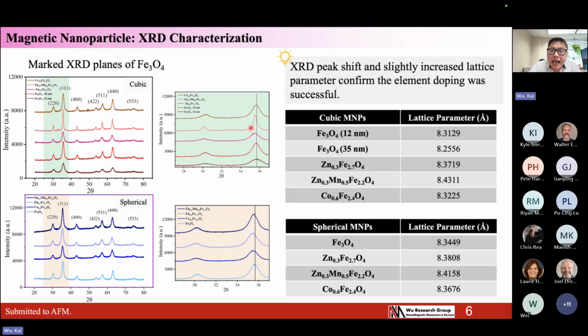This peak shift is evidenced by the lattice parameter of these particles. You can see that with doping of the element, the lattice parameter increases compared to the initial phase Fe3O4, which tells us that we successfully doped this divalent element into iron oxide to achieve different doped ferrite structures. The same thing you can see from the spherical particles. We also see the peak shift of the 311 plane, and we also observe the increased lattice parameter after doping.